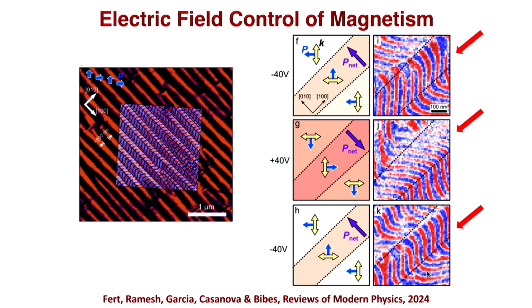Okay, now on the microscopic scale, I showed you this example before with bismuth ferrite. These are the spin spirals. When you apply an electric field to this system, you can actually switch it back and forth. You can microscopically see electric field control of magnetism. When Jan Seidel and a whole bunch of people were in our group, they actually did some beautiful experiments using photoemission-based stuff, linear dichroism. But now you can do all of this with imaging on the very microscopic scale.